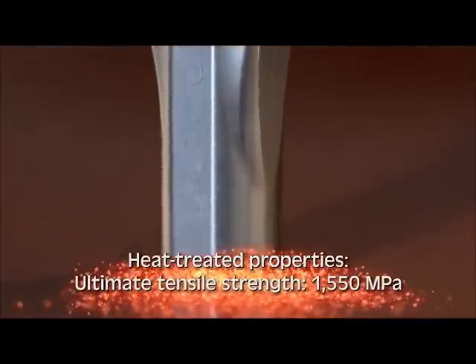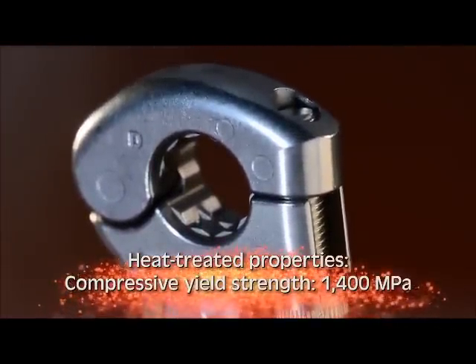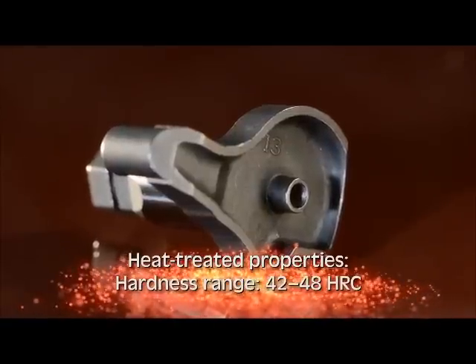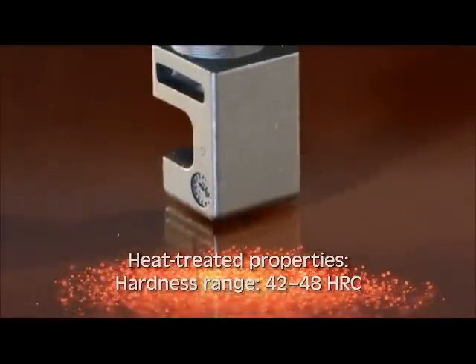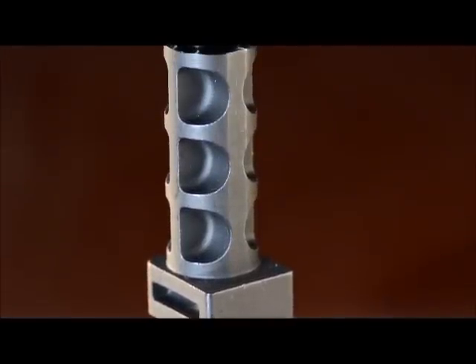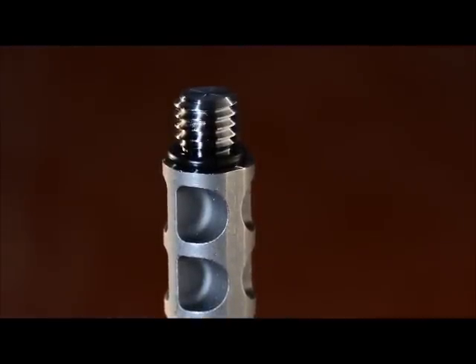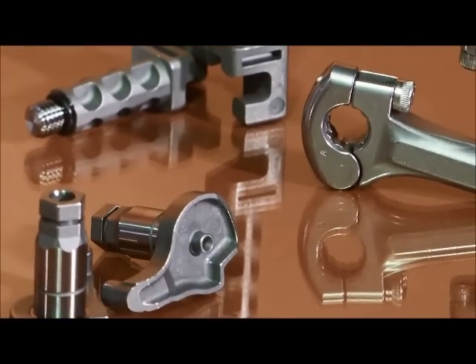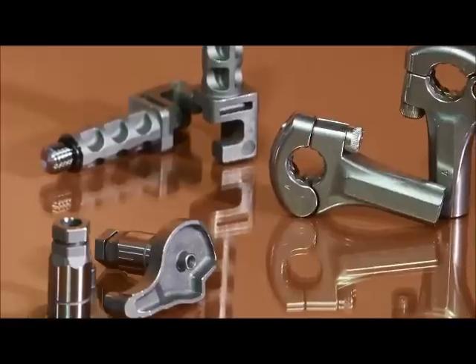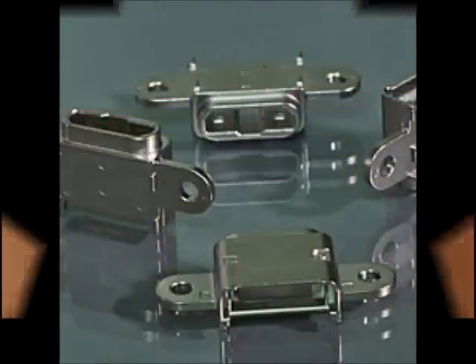All dimensions of the 2 parts forming the new base are achieved in the as-MIM condition, including the internal thread in the body. The catcher receives a grinding and burnishing to attain the OD tolerance and surface finish, while the tension bar needs only a turning operation to form an external thread without a parting line. The parts were formerly produced via machining, welding, conventional PM, and fastening. By completely redesigning the parts to maximize the advantages MIM offers, the customer obtains savings estimated at 65%, with annual production of 350,000.